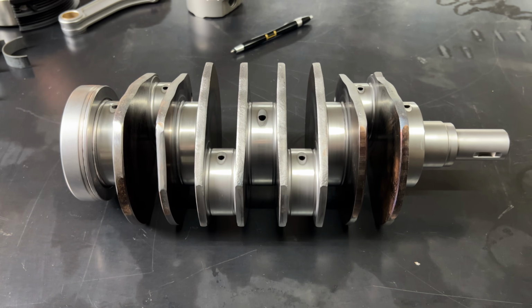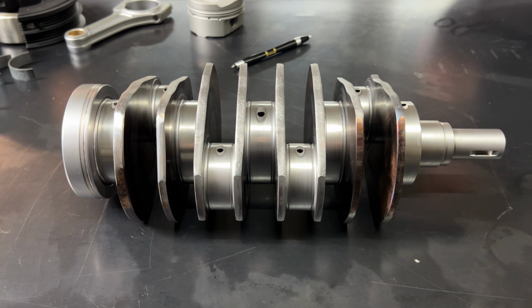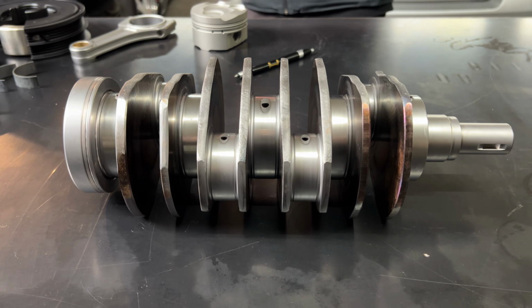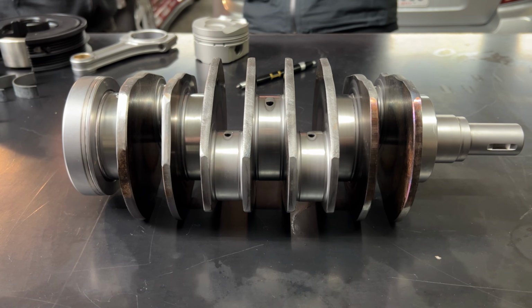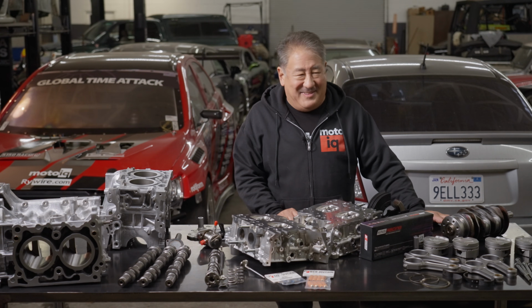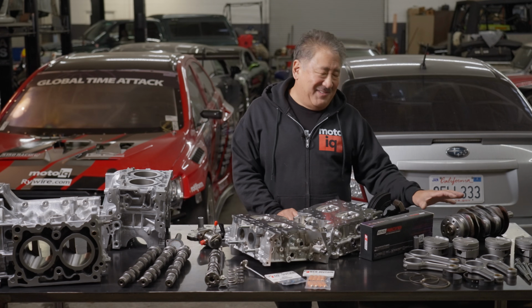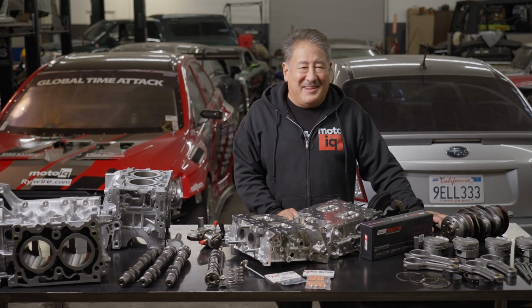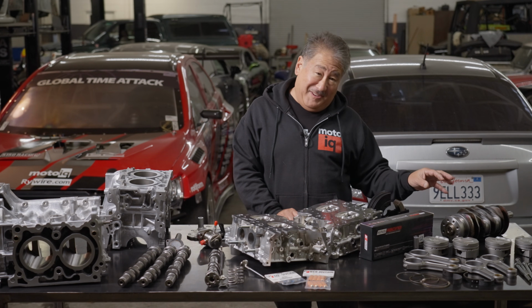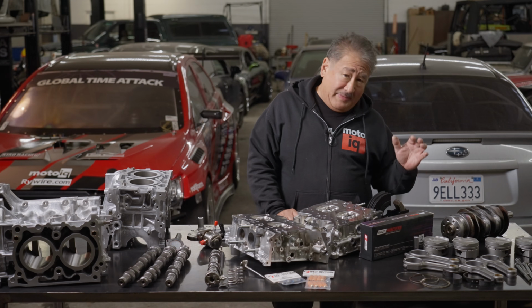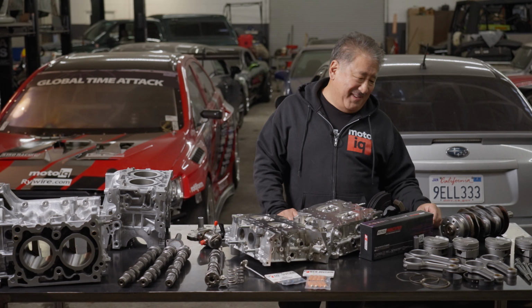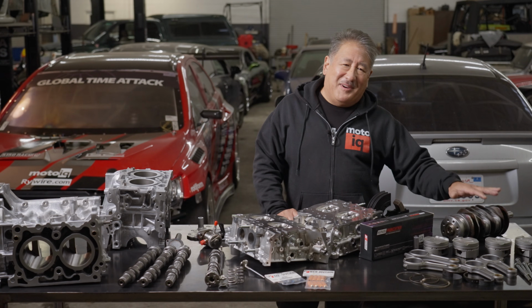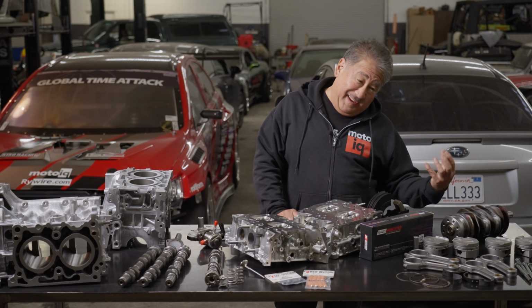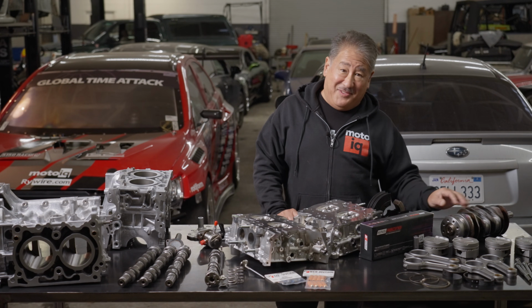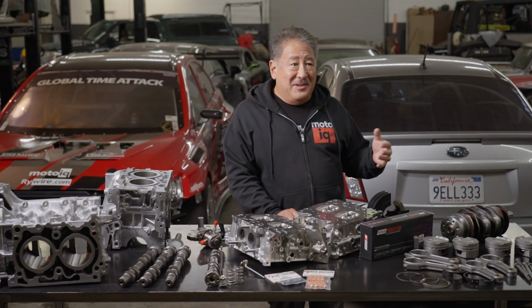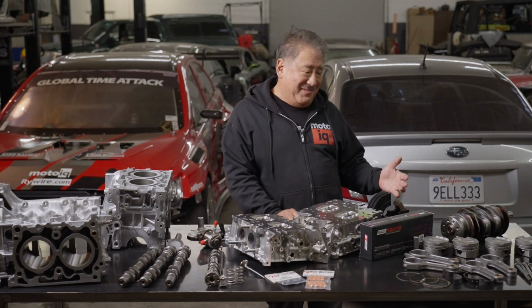We get the crank, we micro polish it, and in this case, we send it to CTP Cryogenics to get it cryogenically treated. The cryogenic treatment stress relieves the crank and also converts the austenite, which is the crystalline metal structure, to martensite. So we're going from a face-centered cubic to a body-centered cubic structure. Martensite is harder and stronger than austenite. There's some martensite in the stock crank, but we're converting more of the austenite into martensite and improving the strength. It's kind of like heat treating. So think of cryo as an extension of the heat treating process.